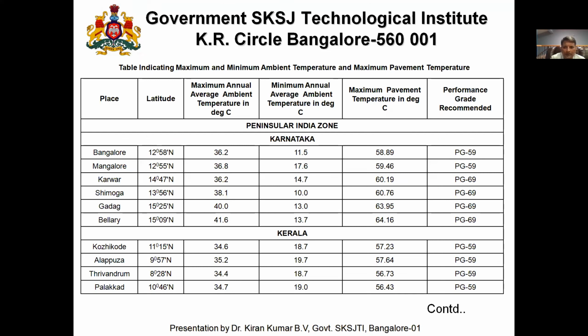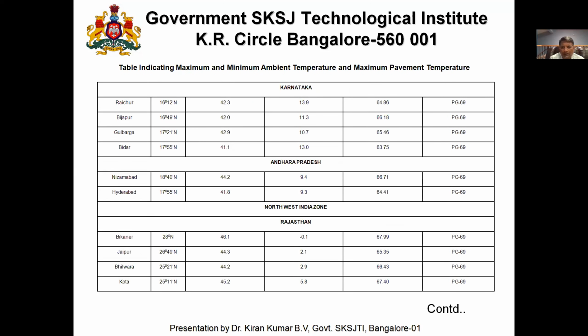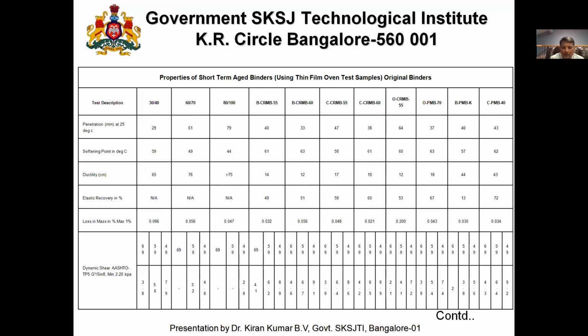Bangalore alone requires a 60 centigrade binder, or a PG grade of 59 to 60, to cater, wherein our softening point of VG40 does not even cross 50 centigrade. So what exactly is happening, where we are failing? Then again, if we use this binder and use the Marshall method to compact, the Marshall method gives us an erroneous optimum binder content, because the carefully chosen aggregate disintegrates. Once it starts disintegrating, the surfaces which are disintegrated require higher binder content, and that binder content cannot be accommodated within the air voids that we are designing. So we are at fault somewhere or the other at the beginning stage itself.